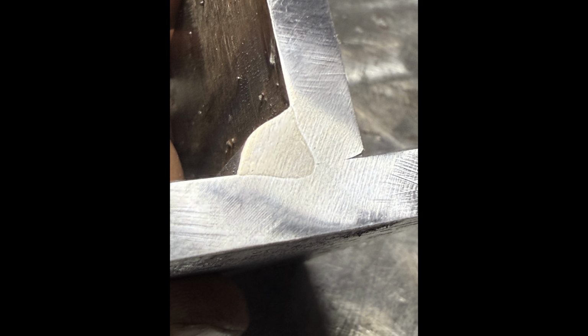Now keep in mind, if you plan on doing a lot of 1/4 inch material, a 200 amp max machine will probably hit thermal overload, or you'll start having things melt in the gun if you do a lot of it. So you want to be careful with that. That's probably the biggest drawback of the short arc MIG process, is that a 200 amp machine, which is your common MIG welder sold at stores that many of you have, is basically maxed out just to weld 1/4 inch thick steel. It's just the reality of the situation, and that's why stick tends to be a better solution, because you can actually get some duty cycle output without hitting thermal overload welding 1/4 inch, because you're only at like 90 amps output to get the same results with stick.